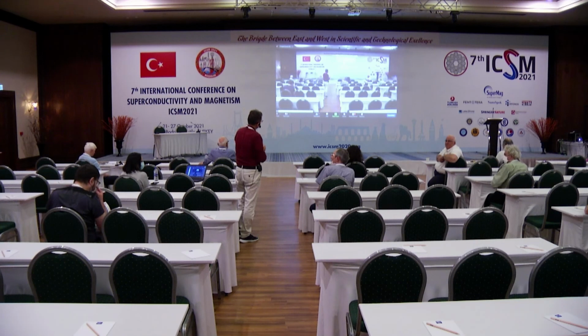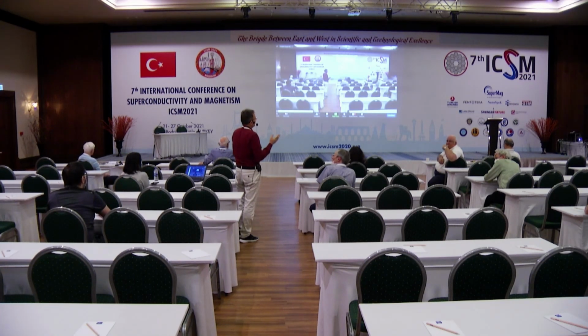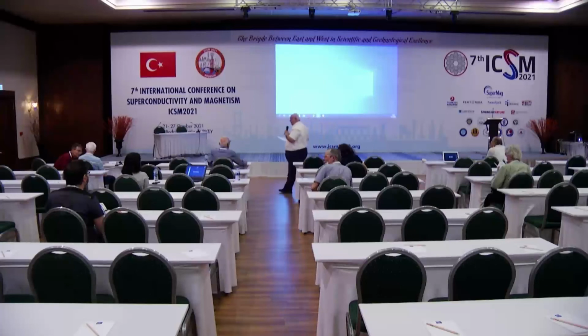Possibly yes, but it would be fantastic because then this superconductivity would exist only in this topological sample. So it would be topological induced superconductivity, and this would be something. We tried to do transport one way or another, and we didn't find any superconducting signal in transport measurements. So we believe that if there is two-dimensional superconductivity somewhere on the surface, I'm pretty much sure that we should have found it. We didn't. Okay, you go on.